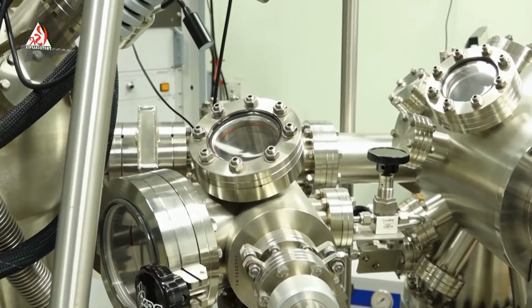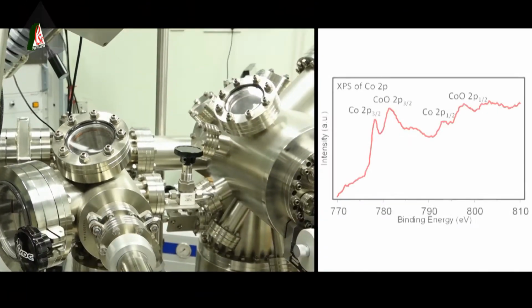While measuring the activity, we found a broad peak before or along with the onset potential, which indicates some irreversible oxidation is taking place. This prompted us to check our post-catalysis sample. XPS study reveals that the surface is converted to oxide or oxyhydroxide.